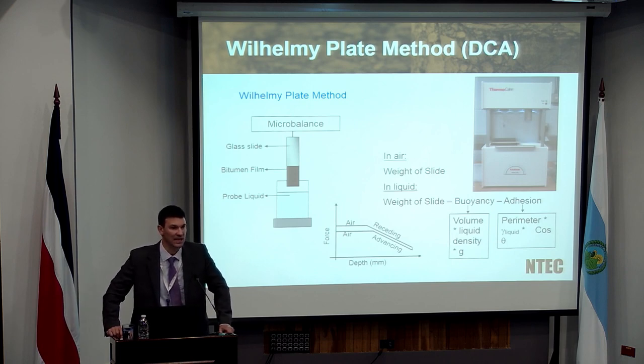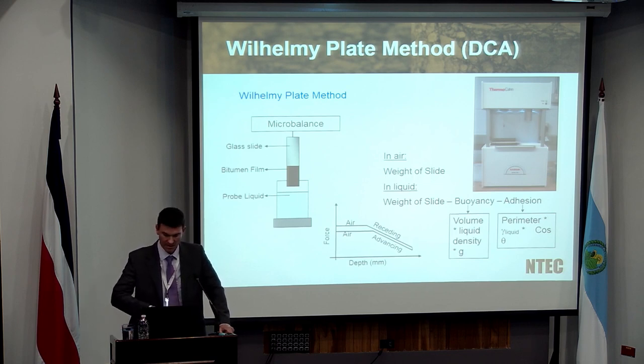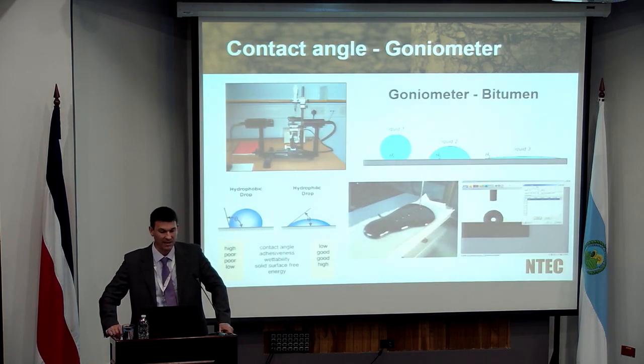It's a dynamic contact method. You measure effectively two different angles, an advancing angle and a receding angle, and you can take either of them really if you wanted to work out your surface energy. So that's quite a quick and easy way to measure surface energy, and that's how we do it at Nottingham. There is a second way which we have played around with, and that's using a goniometer.